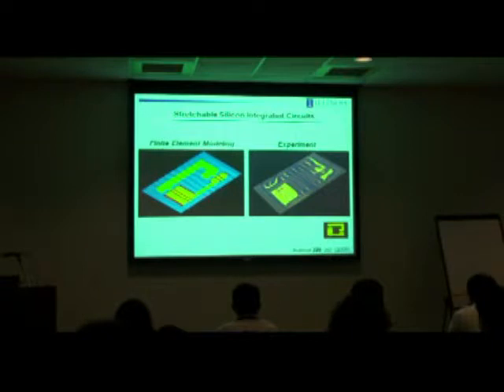Now, what you see is the pattern of waves is actually a lot more complicated than in the case of just these uniform strips of silicon. But that's easy to understand because this circuit is both heterogeneous in materials. Silicon is here, for example, it's not over here, and also in thickness. So the local bending rigidity of the circuit varies depending on where you are in the circuit. So in this particular case, bending rigidity is lowest at these interconnect lines, highest here. So the waves tend to localize in those regions that are more easily bent than the locations of the silicon transistor.